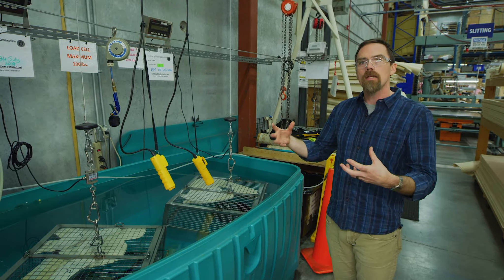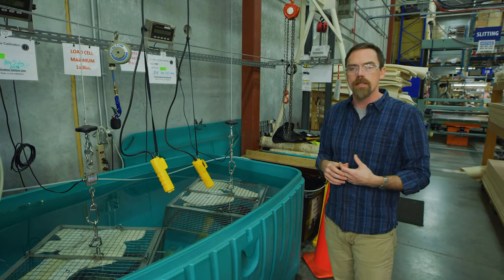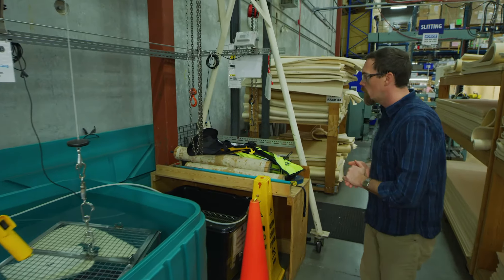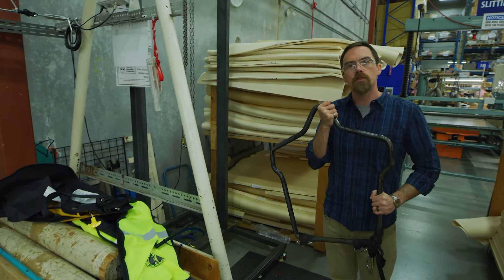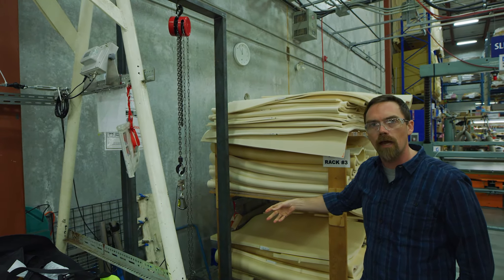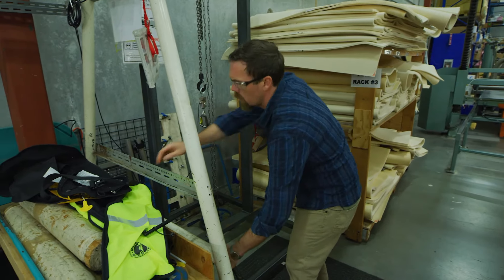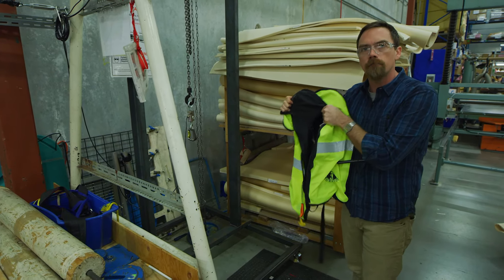Typically, because of the bladder fabric relaxing under pressure, we usually actually gain buoyancy. This is a per-lot test and depending on the size of the lot, it can be anywhere from one to ten units per lot. It's also a destructive test — we don't sell these units. After the six hours, we replicate the situation where somebody wearing an inflatable PFD may have inflated it through the oral tube and then pulled off the CO2 cylinder to create more pressure than intended. We add another 20% on top of that, so it's an extreme pressure event you should never see in the real world.